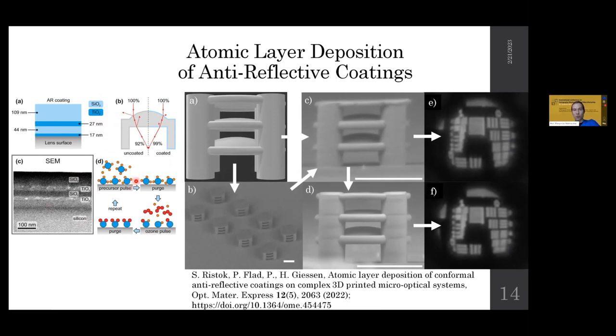We continued on this work, and the first main difference is that our used material was coming from Femtika, SZ2080PM. Also, we managed to make the lenses much smaller, below 100 micrometers. In this case, it's around 70 micrometers, the diameter of a lens, and stack them like multi-layered structures to make compound lens devices. The fabrication was repeatable, as well as the coating.